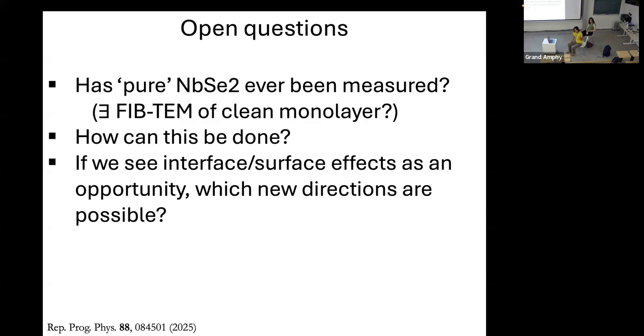So just two things. First is the oxidation. I can believe the selenium is disappearing, but for the oxidation, I'm not sure. Correct me if I'm wrong, but I don't think FIB-TEM has seen any oxygen so far. We cross-section almost each and every device. At least in the tunneling devices, they are by definition encapsulated. And we do FIB-TEM and metal analysis, and we see no evidence for oxygen or selenium deposition at the top surface. So there is a superstition that NbSe2 oxidizes. It will be more accurate to say it degrades in an unknown way, because I don't know anyone who has seen oxygen so far in a FIB-TEM.